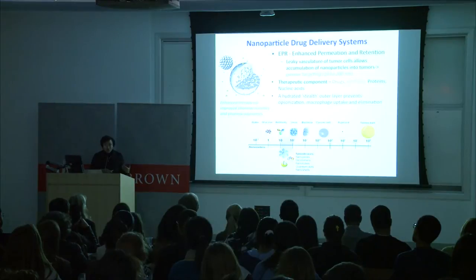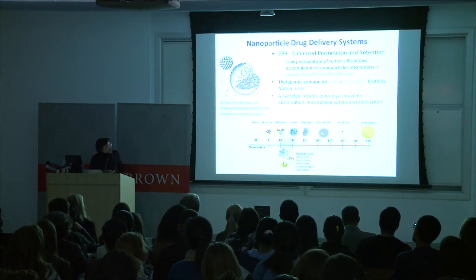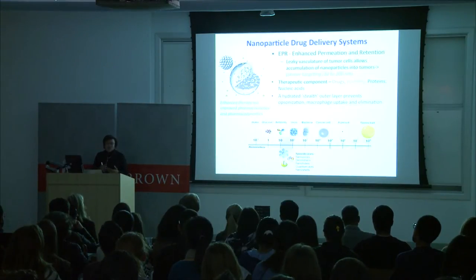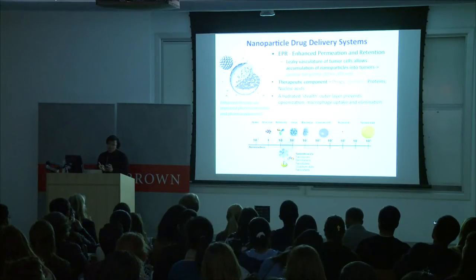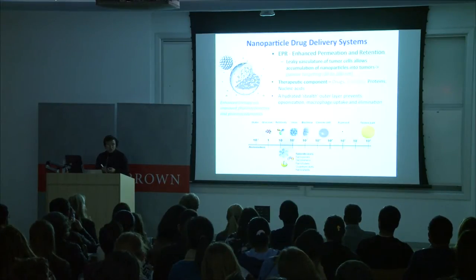So we'd like to be able to design these nanoparticles so that they're not readily recognized by the immune system, by these monocytes and macrophages. We'd like to be able to decorate them so that they look essentially like their surrounding environment. And we often do this by using a polymer layer that gives us a huge amount of hydration. They essentially allow water molecules to bind to the surfaces of these nanoparticles and essentially allow these to, if you can imagine, float around as if they were innocuous water molecules. If we get the closest we can get to that, it will allow us to get these through the bloodstream and allow them to accumulate in the tumor. So this is part of the construction of this nanoparticle vehicle. There is one final thing that we might want to do.